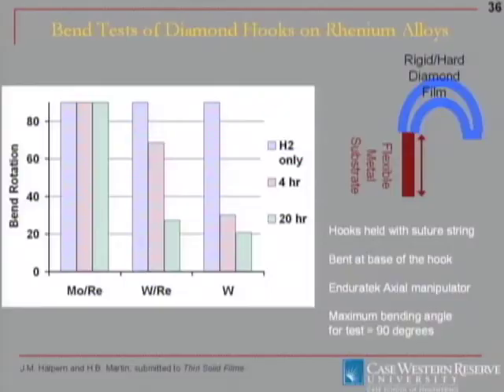Here's our original substrate, tungsten. The control here is just growing in hydrogen, where you're not going to get any diamond, and it should stay ductile, and it does, because the maximum of the test is 90 degrees that we bend it. After 4 hours of diamond growth, that's this red bar here, tungsten breaks after 20 degrees, just snaps right apart. Tungsten-rhenium is better, but the best case is molybdenum-rhenium, where you have to bend it back and forth before you eventually get the substrate to break. So this is very exciting, because this could help not just for biological applications, but in general, this could be a new type of substrate for making diamond electrodes.